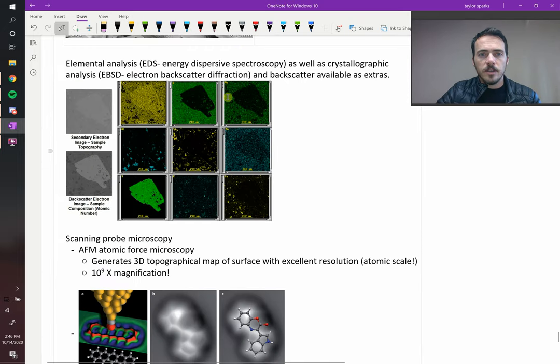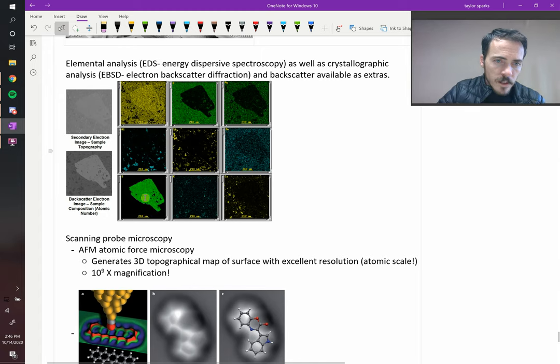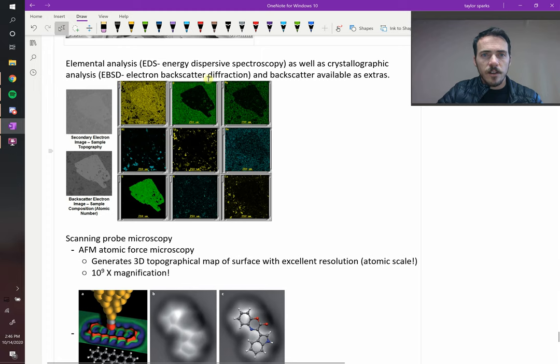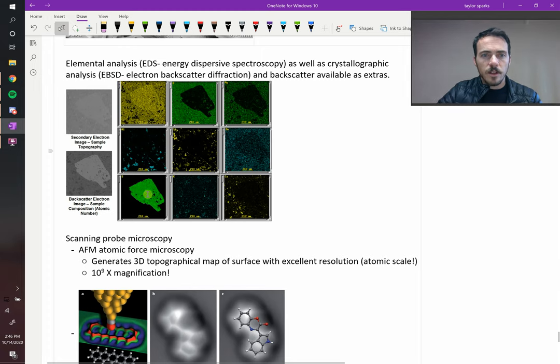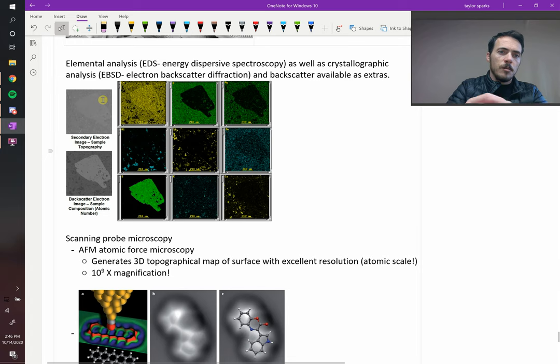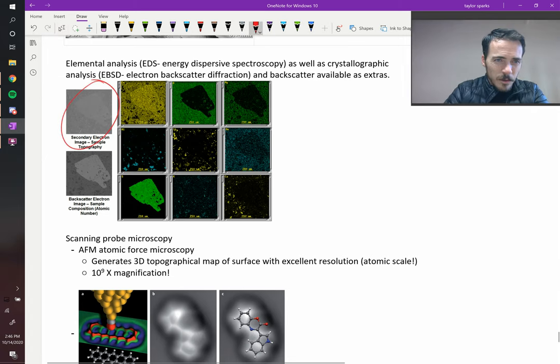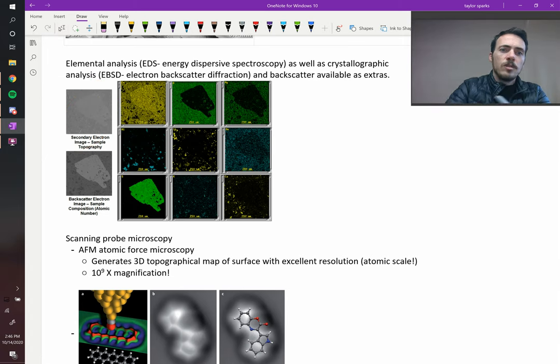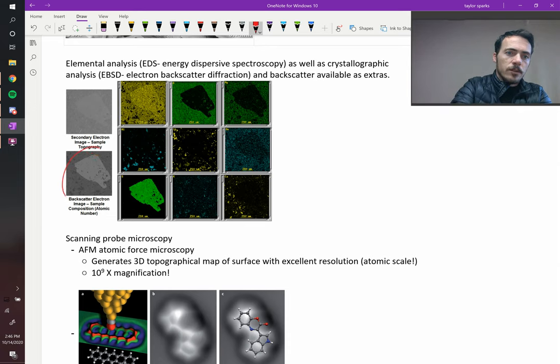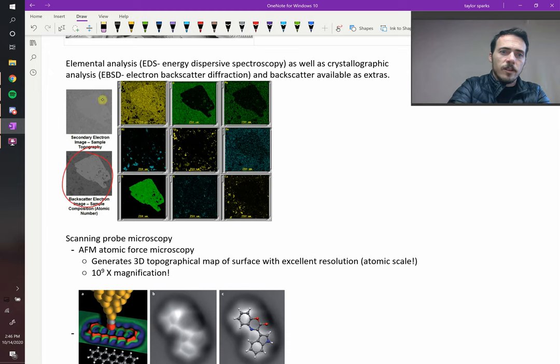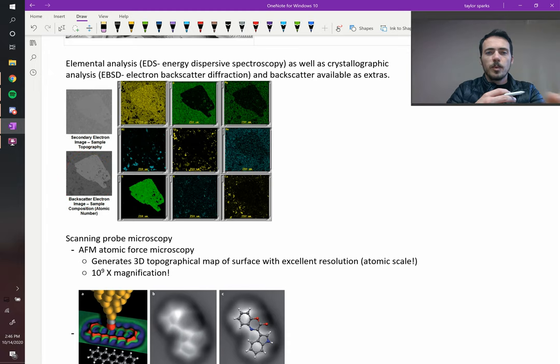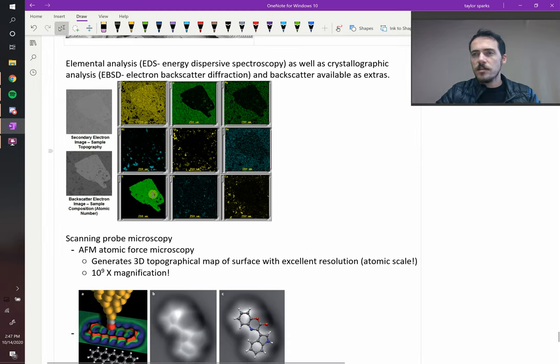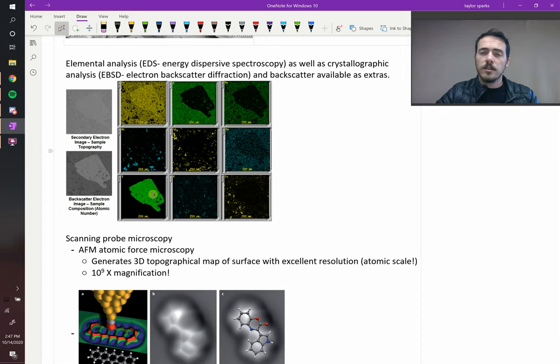And then we've already talked about EDS that you can look at different elements where they are. For example, here we see the green in this frame looks like it belongs to sulfur. And then the yellow looks like it belongs to iron. Then you've got magnesium is this one right over here. So you can see really clearly that this compound here, the inclusion, is sulfur and iron. But again, look at the regular SEM image right up here. It's hard to kind of tell what's going on. You see something there, but you don't have as much information. But as soon as you turn on backscatter imaging, now it's very clear that there's a secondary phase there and you know that it must contain high atomic number elements relative to the other things. And then you do EDS mapping and it just brings all this additional information into it until you can figure out, oh, this is such and such a phase. And if that's not desirable, then you could try and figure out how that ended up in your plant, in your device.